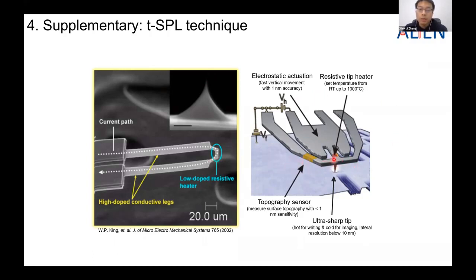And by eliminating the lasers, it can reduce the tuning of the laser part. One sensor is used as the topography sensor to locate the position of the tip. The other sensor is the heater that can accumulate the heat into the tip and pattern the polymers here. So this is a key part of the scanning probe lithography.